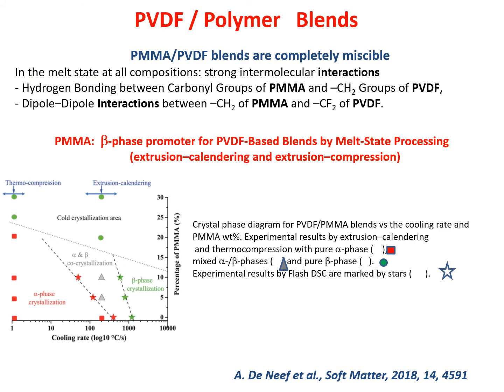The beta phase, alpha phase, and gamma phase, and also by wide-angle X-ray scattering. So this chart is very interesting. I think it has been shown by Jean-Marie in the previous talk. And you can see here that the sample was under an alternating field. You have some nice, different Flash DSC data. You can see that you have different behavior regarding the alpha phase, or a co-crystallization of alpha and beta phase, or beta phase in certain conditions.